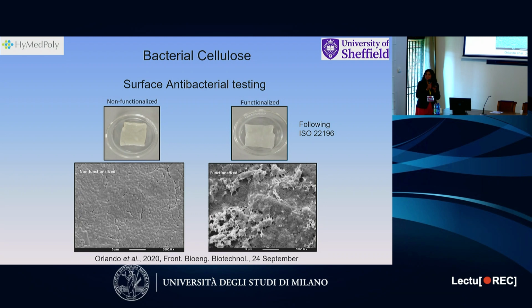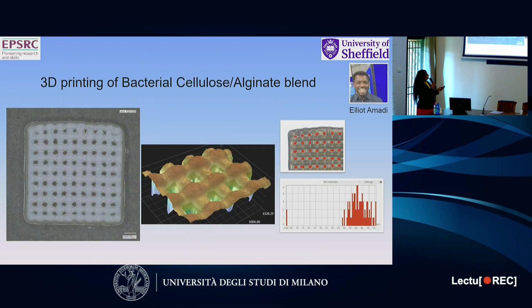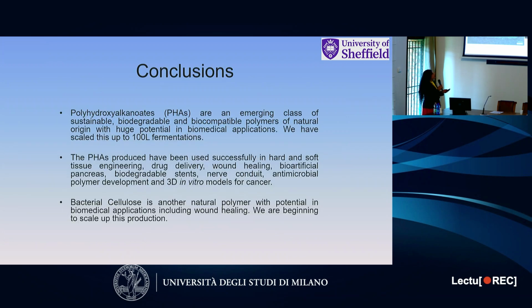We have basically added alkyl groups on the surface, which then cleave the bacterial membrane. And you can see on the left, there's Staph aureus attaching and growing really well on the bacterial cellulose. And on the right, you have the functionalized bacterial cellulose, and the bacteria are attaching and lysing. They can't survive on this polymer. We are now beginning to 3D print this along with alginate. So these are now being worked on for wound healing in my laboratory.